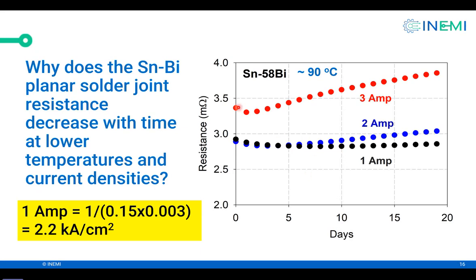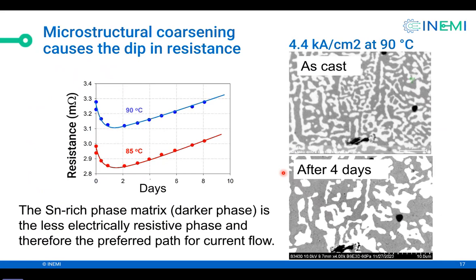So why does the resistance decrease initially? Other people have observed this also, but they have not looked into the physics of this. So let me show you why this happens. The initial decrease in resistance is because the solder structure coarsens. So let me remind you, the bright regions are bismuth. The gray region is tin-rich phase. Over a 4-day period, at 90 degrees C, 4.4 kiloamps per centimeter squared, the structure coarsened.